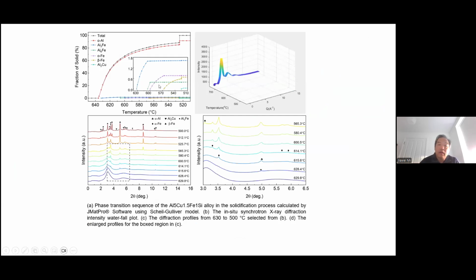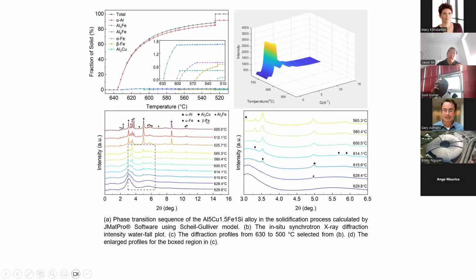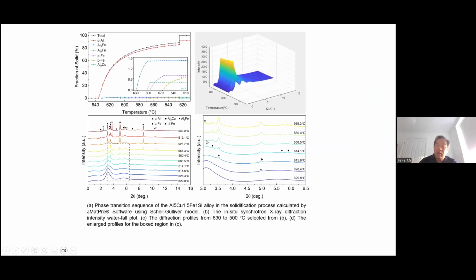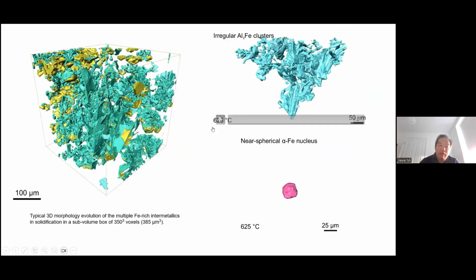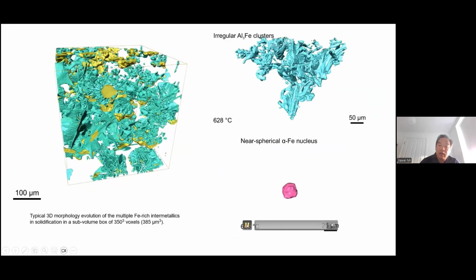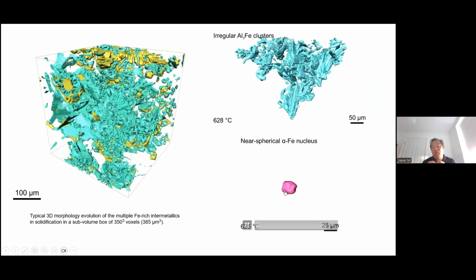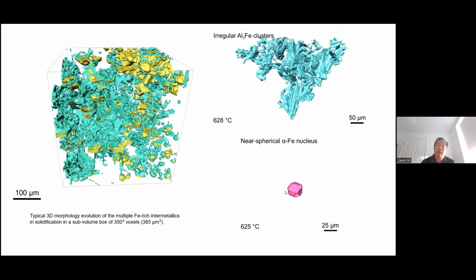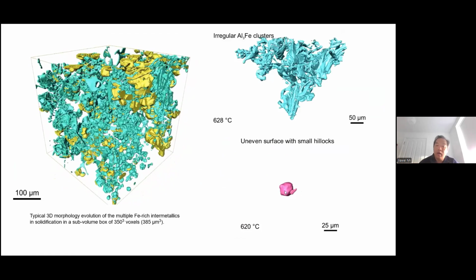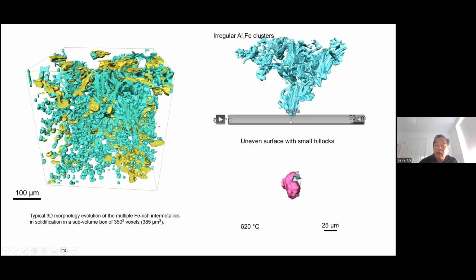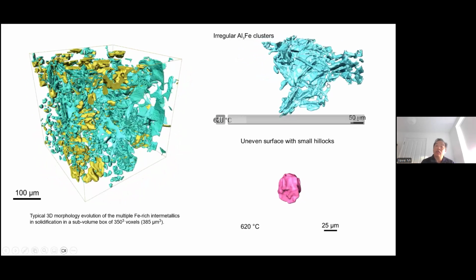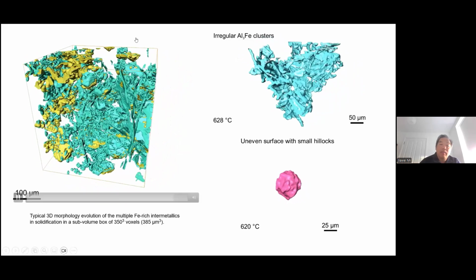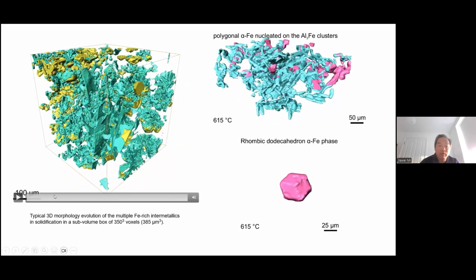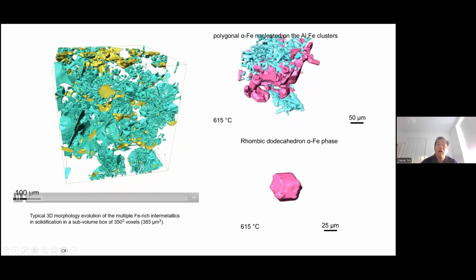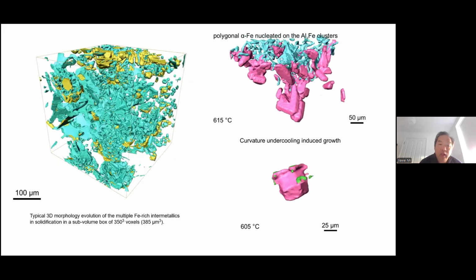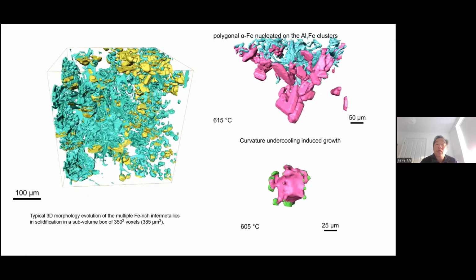And now, because we have fully characterized this starting from very tiny nuclei to the whole growing process, we can now fully understand how, look at this, a single core will develop into the convoluted network structure, which we call the Chinese script type. And this is how the different phases can grow on top of other phases, and then collectively how the alpha phase or beta phase look in the whole volume of these materials. So we fully understand the process.